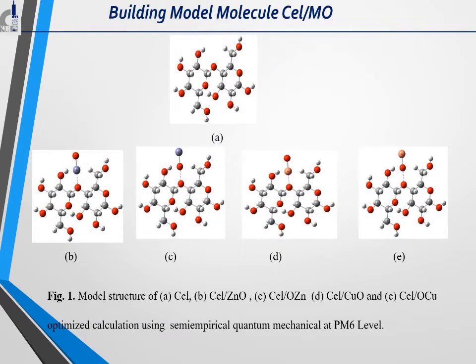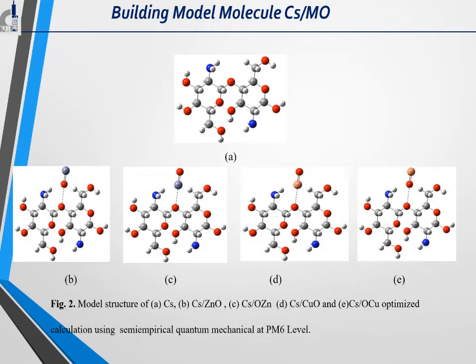Group 1, as shown in figure 1, represents the interaction of two units of cellulose linked through an oxygen atom with zinc oxide and copper oxide, one metal atom and one oxygen atom, which interacted with the polymer through the linked oxygen. As well, group 2, shown in figure 2, represents chitosan interaction with the metal oxides zinc oxide and copper oxide with the same mechanism of interaction. Also, figure 3 represents the sodium alginate group with metal oxide interacting with the same mechanism.